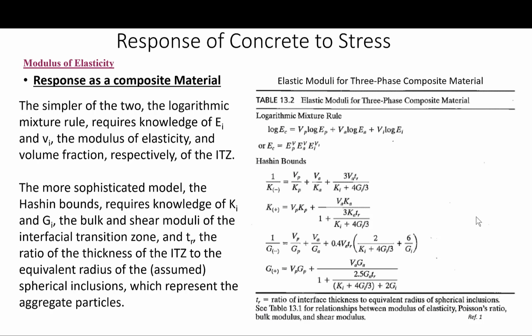For similar concrete containing silica fume, the ratios lie between 0.5 and 0.88. This demonstrates greater density of the ITZ when silica fume is used in concrete.